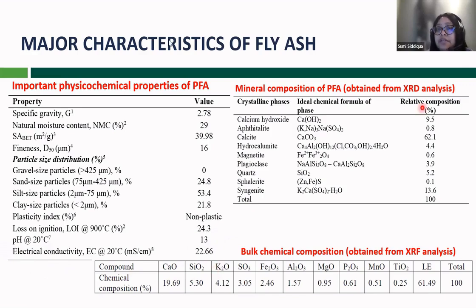We also wanted to look into the mineralogical composition based on the XRD. And we have seen the calcium hydroxide is much higher in percentage, which is 9.5%. And also calcium carbonate, the calcite, is also 62%. So which are good news for us because these are the good minerals that can be used for the construction